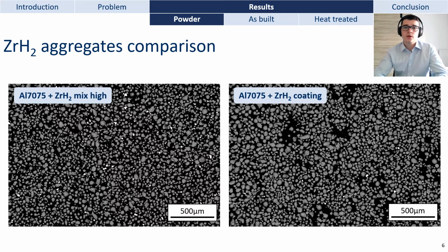Afterwards, we used low magnification SEM images to analyze the quantity of zirconium hydride particles that are present in the different powders. The aim of the zirconium addition is to have small zirconium particles grafted on the aluminum powder. The big particles that appear in white on the SEM pictures are zirconium hydride particles. These large particles will be detrimental for the mechanical properties of the parts, and so we want to avoid them. Indeed, they will either form some large precipitates or stay unmelted and serve as preferential damaging sites.